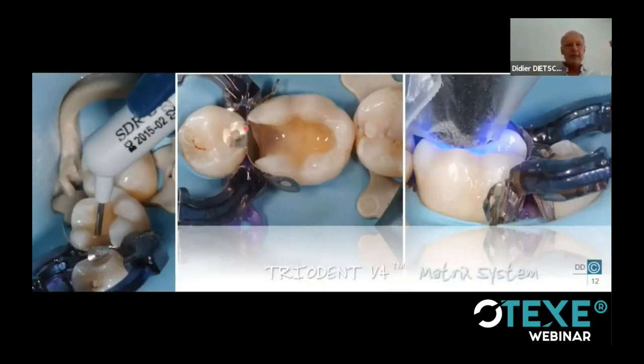So why not use flow? I like to use flow when the cavities are really deep, where it is a little bit difficult to keep the matrix in contact. You don't want to condense a heavy, highly filled material. I think the flow here has very good consistency. So I was using the SDR flow, a bulk filling material. That's basically the most well-known material in this category.